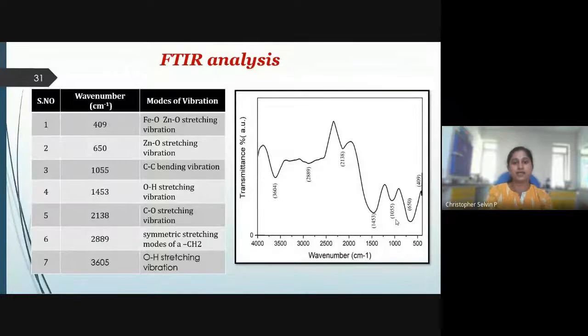Followed by that, we have FTIR analysis, which indicates the vibrational peaks of the different modes. Initially, the low wave numbers are assigned to the metal oxide, whereas the higher wave numbers are assigned to the metal hydroxide complexes. So this region is ascribed to the vibration of the metal oxide region, that is this region, whereas the higher wave number region can be ascribed to the metal hydroxide interaction.